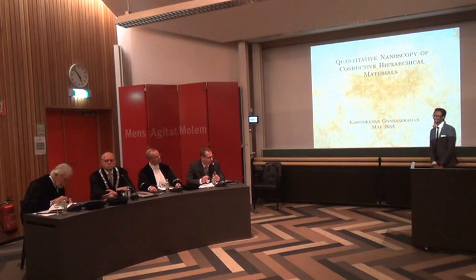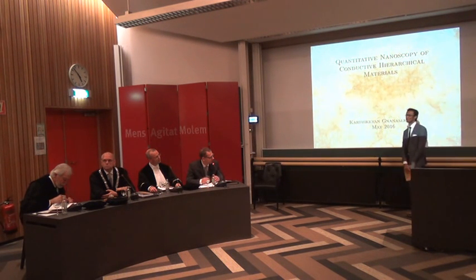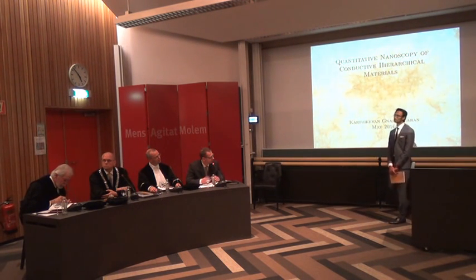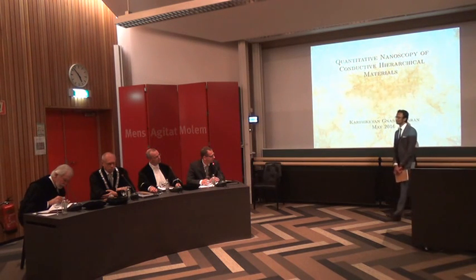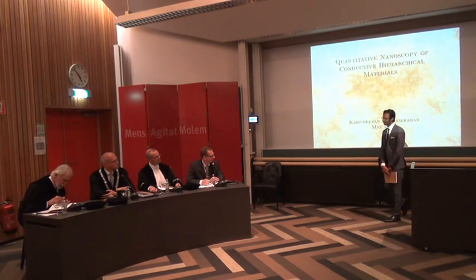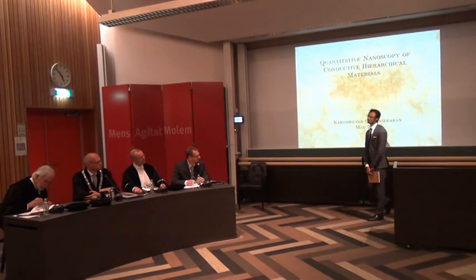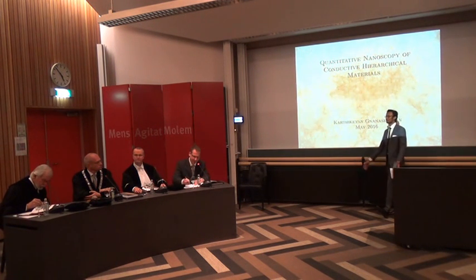So then, would you be able to make an estimate of how much time it would take with the tools that you develop to acquire this 1 cubic millimeter nowadays? Yeah, for me it takes three, three and a half complete full days, including the image processing and the stitching and all these things. It will take maximum 5 days.